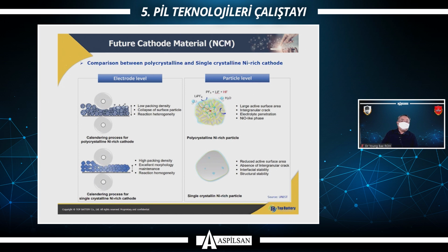The polycrystalline particles generally have a low packing density. The surface particles partially collapse under high pressure, and heterogeneity of reaction appears in the electrode during charging and discharging. But single crystalline particles generally have a high packing density and excellent morphology maintenance under high pressure, and homogeneity of reaction appears in the electrode during the charging and discharging process.